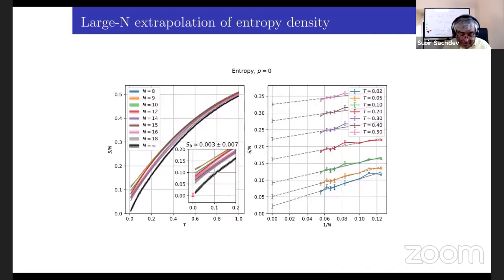So another thing, this is very preliminary, that Alex has worked out, is to try to extrapolate to the zero temperature limit in the following way. For each temperature, you extrapolate the value to n going to infinity, and then you plot the extrapolated value as a function of temperature. So what you find at zero doping, where you have a spin glass state, is that the entropy does go to zero. In fact, this is the entropy per site, and in the classical spin glass, despite the large degeneracy of states and replica symmetry breaking and all of that, the entropy per site does go to zero, even in the Parisi solution. So that's great. You're getting entropy going to zero here.